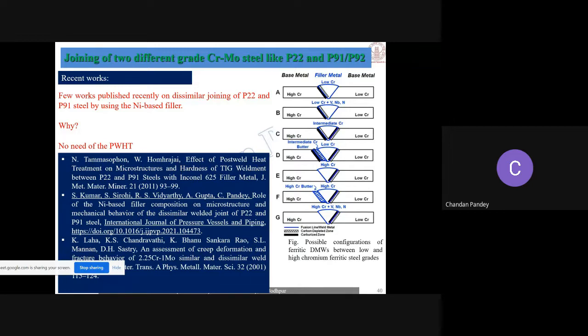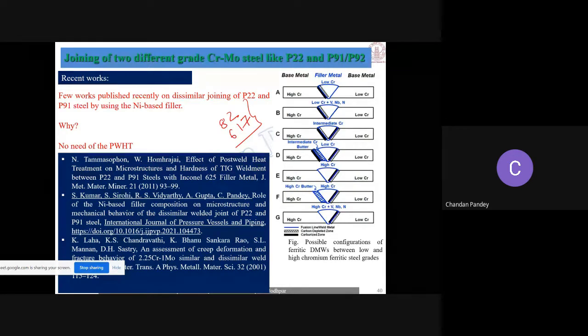Generally we need post weld heat treatment in case of martensitic steel. If we talk about austenitic steel, we don't require any type of heat treatment. So that's why we can use nickel based filler, and most commonly we use 82 and 617 Inconel filler to make a joint of 22 and 91 steel. We can also use some interlayer to stop the diffusion of carbon from one side to the other, or from base metal to weld metal. And by stopping the diffusion of carbon during post weld heat treatment, we can improve the overall performance of that dissimilar weld joint.